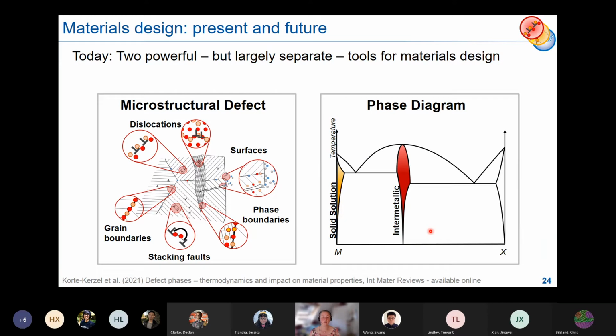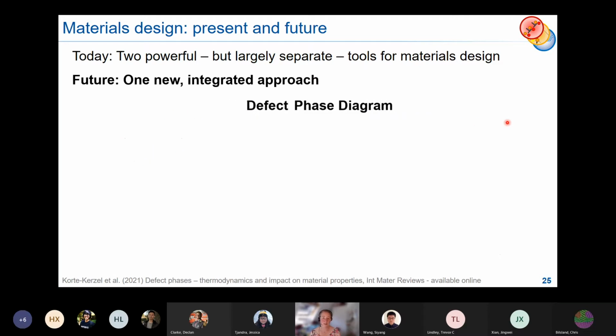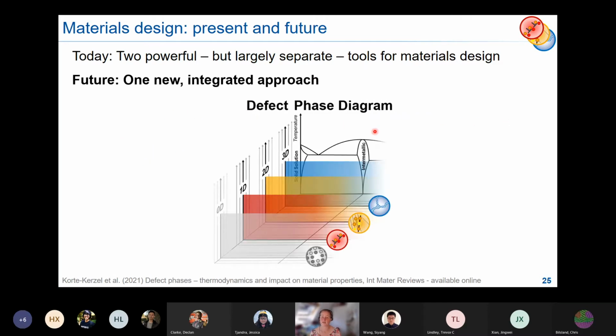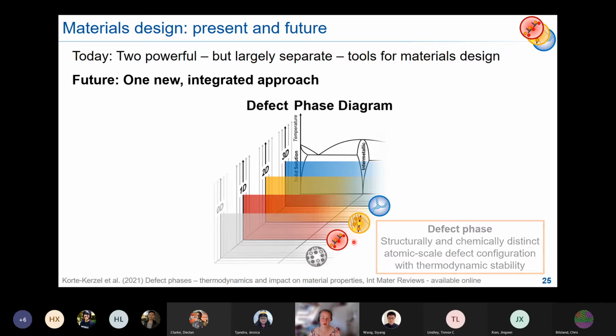So the idea is that what we should be setting out to do is to take these two powerful approaches, thinking about microstructural defects that we tailor and engineer, and thinking about the phase diagrams that we look at, and really put them together in one new and integrated approach, so that we have defect phase diagrams and not just phase diagrams. That means we have to now do the whole exercise of judging stabilities, comparing different possibilities for defect structures in all dimensions. For example, we have the 3D crystal, or the crystal structure. We also have interfaces at 2D, 1D, we have dislocations, and we also have point defects. And we'll try and put all of these into one framework, really.